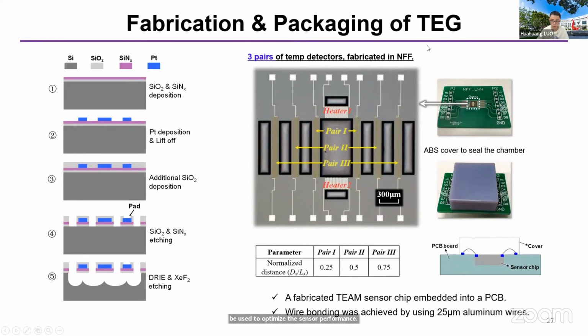Here we show the fabrication and package of the thermal expansion-based gyroscope. The fabrication process is shown in the left figure. It mainly consists of 5 steps in this process flow, and the process starts with the growing of the low-stress nitride and silicon dioxide, and the platinum thin film is deposited and patterned by the lift-off process. In the final step, deep RIE and xenon difluoride etching are used to release the bottom silicon substrate. The fabricated sensor chip with two heaters and 3 pairs of temperature detectors was embedded into the PCB and wire bonded with aluminum wires. And we can see an ABS cover was used to seal the chip to form a chamber filled with the working fluid.